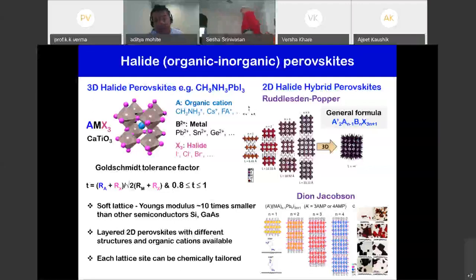Another very interesting thing about these perovskites is that you can also have two-dimensional versions of this, which are known as layered 2D perovskites. And here are two examples of this. So here's a 2D halide perovskite, and it has a well-known structure, which is known as the Ruddlesden-Popper phase. I'll talk about that a little bit later. But briefly, you have this perovskite octahedra, which I was talking to you about, and they are separated by organic cations, right? In this case, the organic cations are quite bulky. And so you'll see you have a layer of the perovskite octahedra, then an organic cation, perovskite octahedra, organic cation.